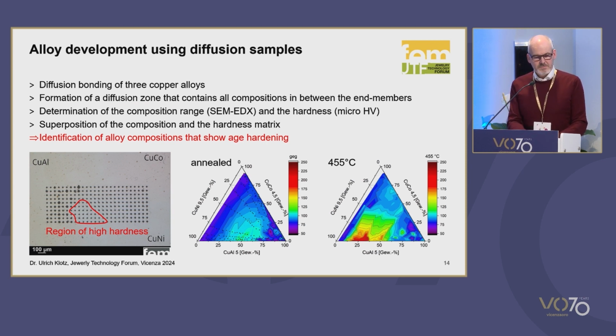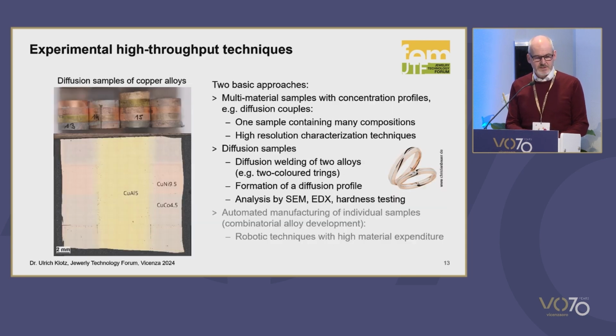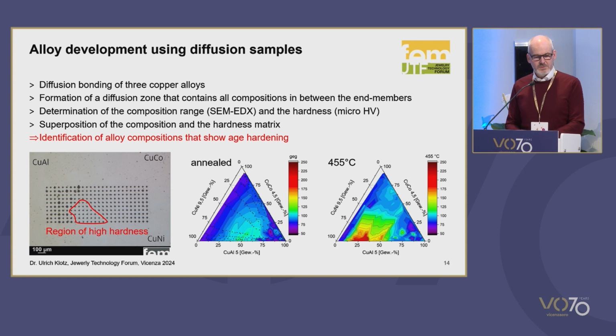So you see the 3 different alloys from this example. You can see them here in 3 corners of this image. And the points that you're seeing here are hardness indents. And you can already see by eye that in some regions the hardness indents are larger. This means the alloy is softer, and in some regions they're smaller, so the alloys there are harder. Now we have to match the composition of the alloys with their hardness.